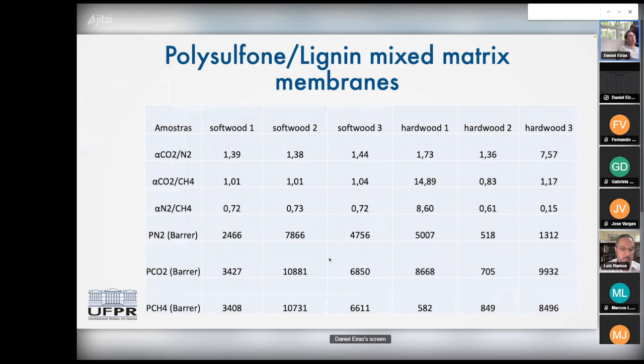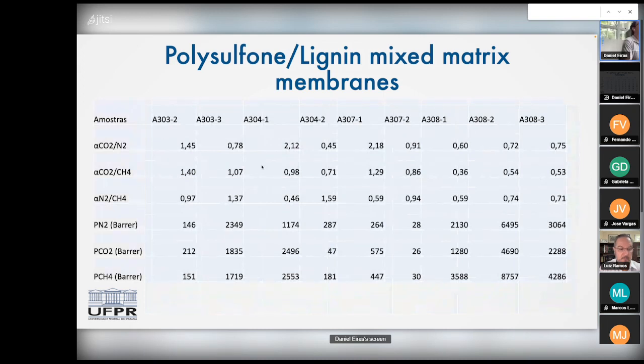When you incorporate only lignin in the polymer membrane, we have a huge increase in permeability compared to the pure polymer. Here the CO2 permeability is supposed to be around 5 or 6 thousand Barrer, but we don't have a lot of selectivity. Some of the results here show some selectivity, but in most cases, what we have is a selectivity close to 1. That means basically no selectivity. The same thing happens when you incorporate the lignin iron nanoparticles. We have huge increases in permeability and no selectivity.